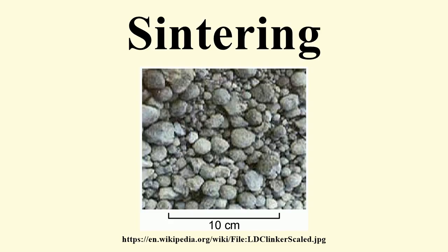For liquid phase sintering to be practical, the major phase should be at least slightly soluble in the liquid phase and the additive should melt before any major sintering of the solid particulate network occurs. Otherwise, rearrangement of grains will not occur. Liquid phase sintering was successfully applied to improve grain growth of thin semiconductor layers from nanoparticle precursor films.